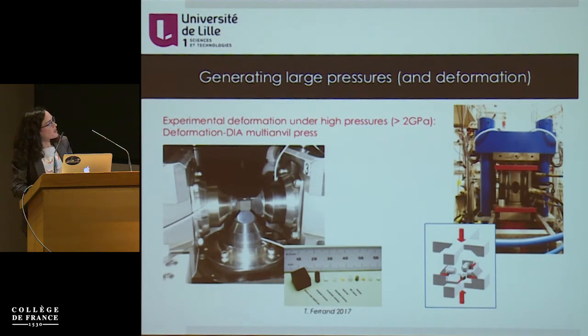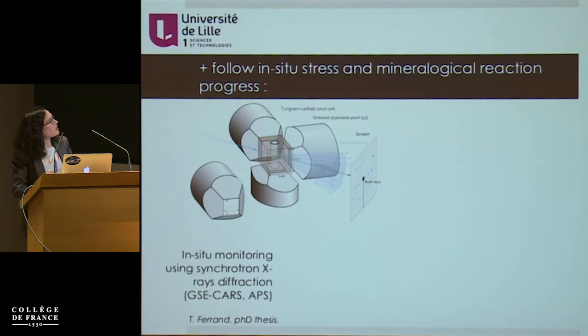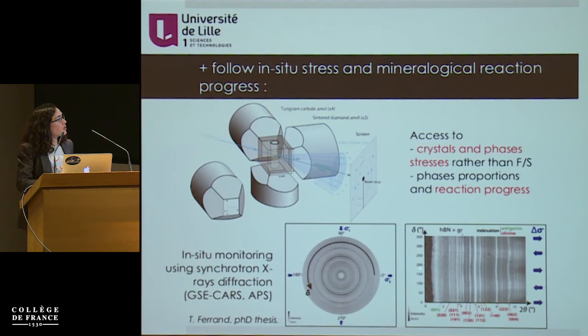So the nice thing about this is you can add, actually, if you have a transparent environment for your sample, an X-ray transparent environment for your sample, you can add in situ monitoring using synchrotron X-rays. And so the X-rays are going to cross the pressure transmitting medium, the sample, and get some diffraction signal, for instance. And the good thing about that is we can measure this diffraction, and from this recover some information on the stresses and the reaction progress within the material.